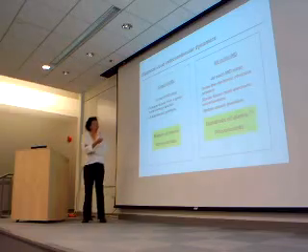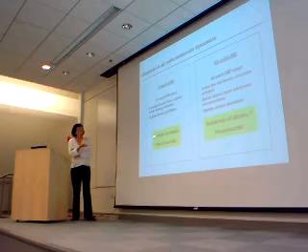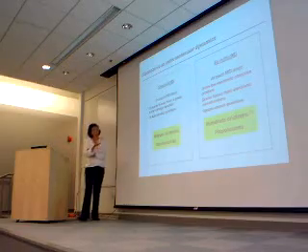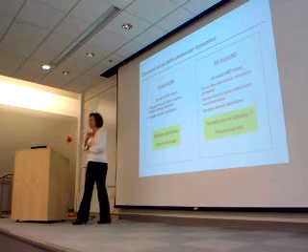These days, not on any laptop or workstation, but with moderate-sized computers and with reasonable range potentials, you can deal with millions of atoms and also nanoseconds for classical MD. Usually, with ab initio MD, we are limited to hundreds of atoms and picoseconds.